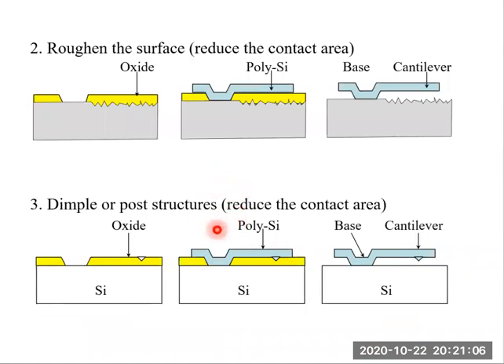We can also avoid stiction by roughening the surface. For example, as shown in this figure, we roughen the substrate. Then deposit and pattern the oxide sacrificial layer. Then deposit and pattern the polysilicon structural layer. And remove the oxide sacrificial layer using HF solution. So it's a wet process.